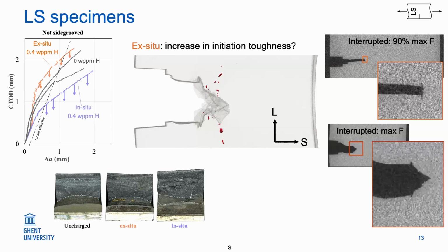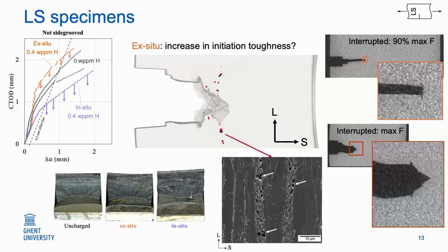And if we then interrupt the test at maximum force, the crack has grown beyond it. But of course, this split will have retarded the crack growth in our CTOD measurement, because it's our crack arresting split. And then if we look at the voids, we can see they are nicely aligned again in a band, and no surprise, again, these are the bainitic bands. If we then look at the cross section, we can see void formation happening in these bainitic bands.